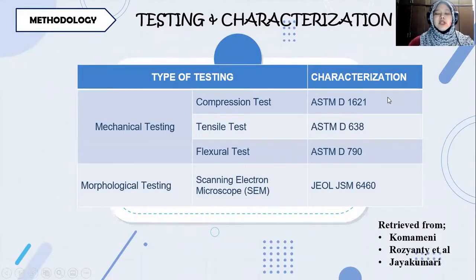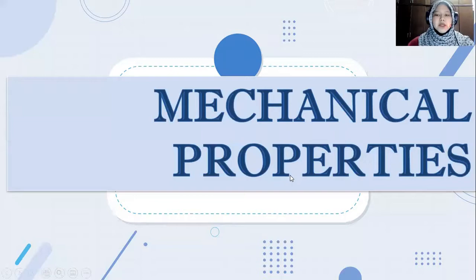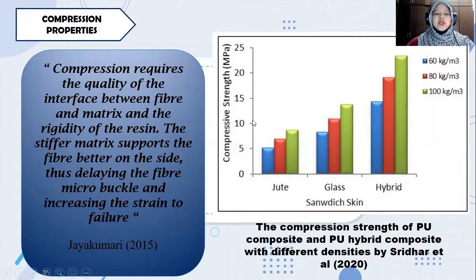This is the testing and characterization used by other researchers: mechanical testing, such as compression test, tensile test, and flexural test, and for morphological testing, they use SEM, scanning electron microscope. Next, on the mechanical properties. First, compression properties. Compression depends on the quality of the interface between the fiber and matrix and the rigidity of the resin. A stiffer matrix supports the fiber better on the side, thus delaying fiber microbuckling and increasing the strain to failure. This graph shows the compression strength of polyurethane composite and polyurethane hybrid composite with different densities by Sridhar et al. in 2020. As you can see, the hybrid has the highest compression strength among the materials. This proves that hybrid can enhance the compressive properties of the materials.